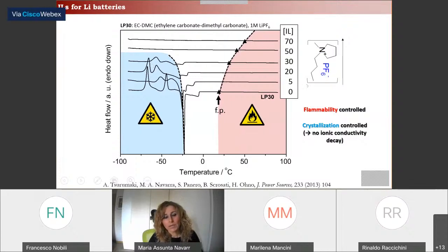Here, for example, we demonstrated that this pyrrolidinium-1,4 PF6 ionic liquid could enhance the flash point of commercial LP30 electrolyte, thus improving its stability. And also the crystallization of LP30, occurring just below 0 degrees, is shifted towards lower temperature and also suppressed with an increasing amount of the ionic liquid. So by controlling crystallization, the ionic conductivity decay can also be controlled, and this is another positive effect due to the ionic liquid addition.